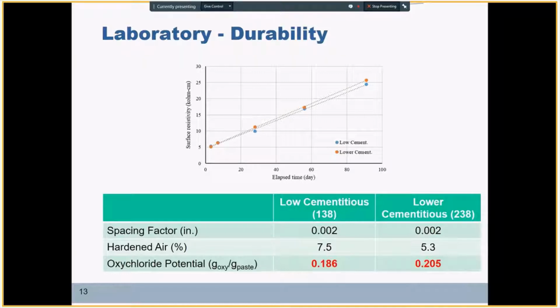The only concern with the durability data was the numbers we got for potential oxychloride formation. We did the low temperature differential scanning calorimetry test, and the LTDSC test data we have are 0.186 and 0.205 for the potential oxychloride formation in these two mixtures. Typically, a number less than 0.15 correlates well with long-term durability against oxychloride formation, which can be manifested in terms of joint damage.